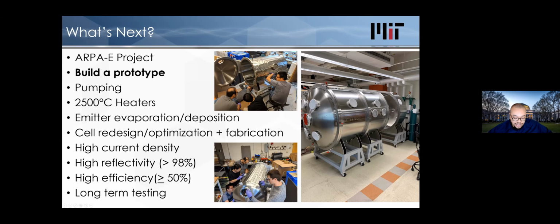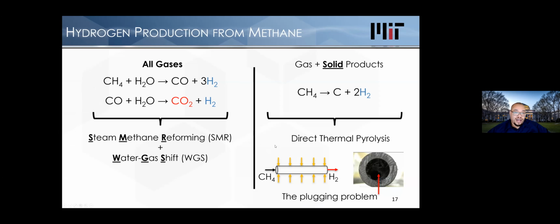So with that, I'll move on to the second technology that we're developing, which is a methane pyrolysis reactor. So this is a completely different problem, no longer talking about energy storage. If you think about hydrogen, the way we make hydrogen today is through a process called steam methane reforming. Essentially two reactions. What you do is you take methane, which is carbon bonded to hydrogen, and you react it with water. Water's got hydrogen in it and oxygen. You end up essentially exchanging the bonds. You want the oxygen from water to go with the carbon so that you can make carbon monoxide first and then later CO2. What's driving this reaction is the thermodynamic driving force to make CO2. Okay, that's how you're liberating the hydrogen. So there's really no way around this other than making CO2.